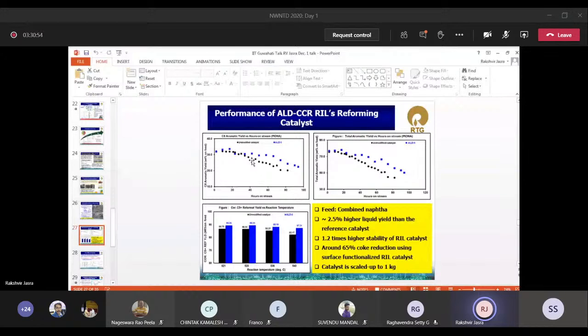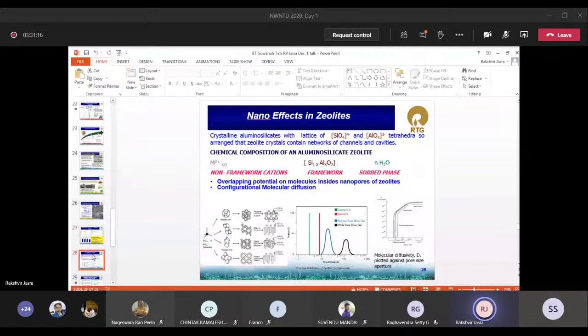And now we have scaled up this catalyst to 1 kg scale. Now we have gone to 10 kg. And we are now in dialogue with some companies to manufacture this catalyst on tons of scale so that we can put it in our plant. So this is how you can really make a big change in your catalyst. The whole ability to put a nano sheet on your catalyst surface to check the sintering is the key development which we have done. The second catalyst which we developed is related to zeolite, which is a nanoporous material.